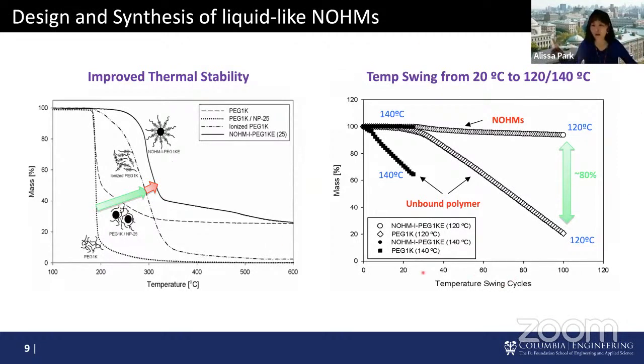Over 100 cycles, NOHMs are very, very stable, compared to untethered polymer, which degrades almost 80%. For CO2 capture application, as I mentioned, we need to use these materials for thousands and thousands of cycles to be economical. So it was very important for us to use the NOHMs, which give very good thermal stability. And in fact, I don't think I'm going to show the data, the oxidative thermal stability of NOHMs was much better than any of the untethered polymer, which is very important for our systems for CO2 capture.